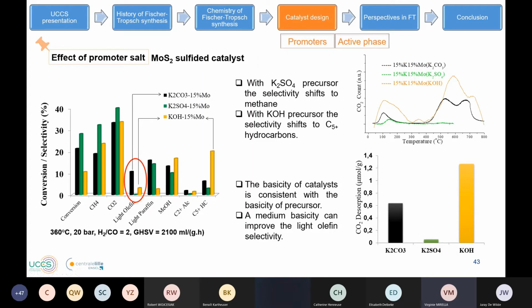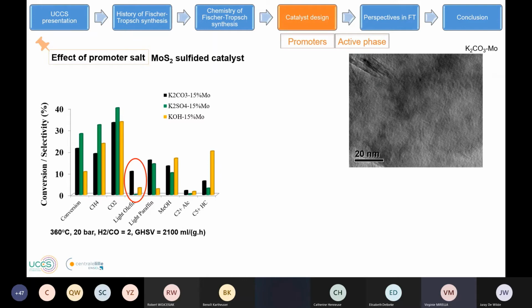For further studies, we have done CO2 TPD, temperature-programmed desorption, to study the basicity of our catalyst, and we observe that when we have KOH, we have high basicity sites, and when we use potassium sulfate, we have too low basicity sites, meaning that to have a high or interesting selectivity in olefin, we need to find a good balance in the basicity of the catalyst. The basicity comes from the addition of potassium.